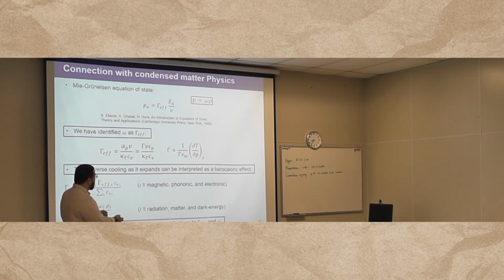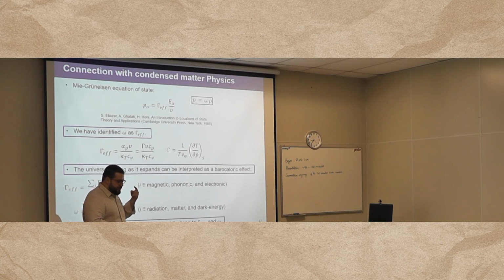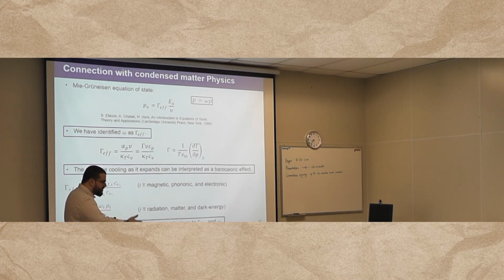But essentially, the Grüneisen ratio I showed you before that quantifies caloric effects represents the singular portion of the effective Grüneisen parameter. The difference is that the effective Grüneisen parameter incorporates other quantities like the isothermal compressibility and the specific heat at constant volume. So this enables us to conclude that the effective Grüneisen parameter is a summation of all contributions in a solid associated with magnetic, phononic, and electronic, in the same way as omega can be written in terms of all contributions to omega and energy density associated with radiation, matter, and dark energy. So this is the key result of this part, because we have recognized that a parameter that is usually constant actually has a deeper physical meaning, and this is the effective Grüneisen parameter.